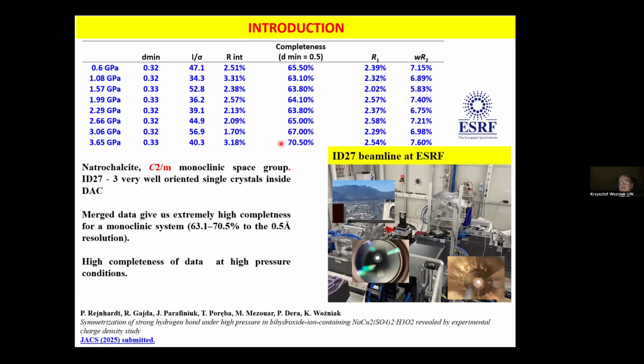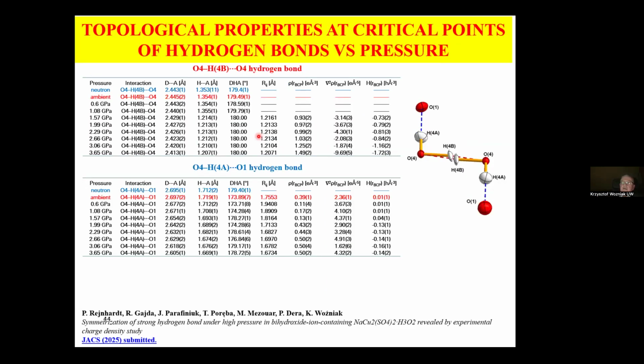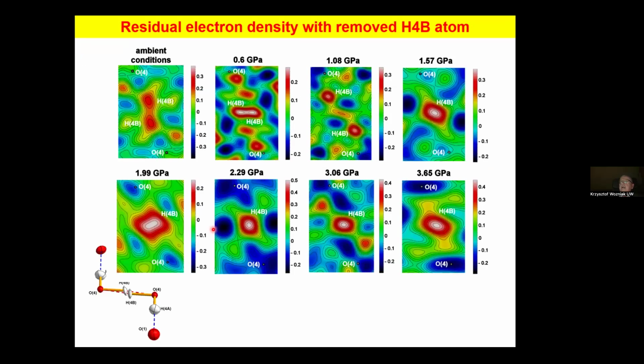Again, we got excellent data from ID27 at ESRF for three very well-oriented single crystals inside DAC. That's what I'm stressing. Especially in the case of low symmetry crystals, one should orient them in DACs just to maximize the number of reflections available. And we've got pretty good data. I wouldn't say, I mean, the completeness is only 64 up to 70%, but this is monoclinic system. But the data are very consistent. The values are really, I would say, very reliable.